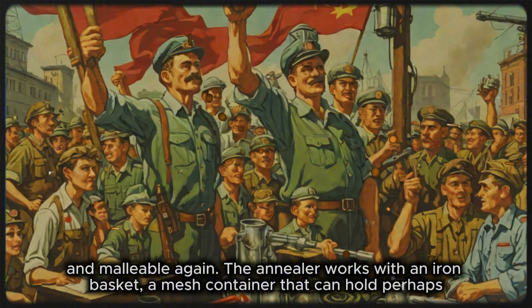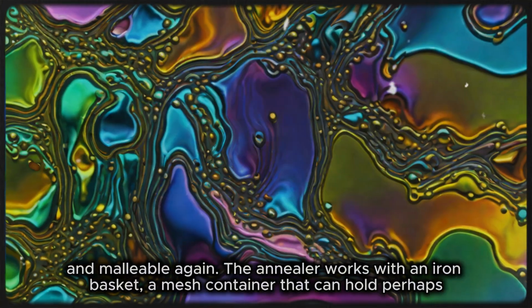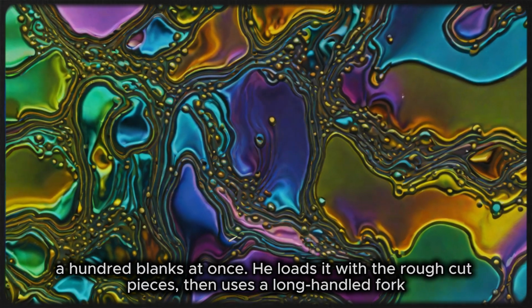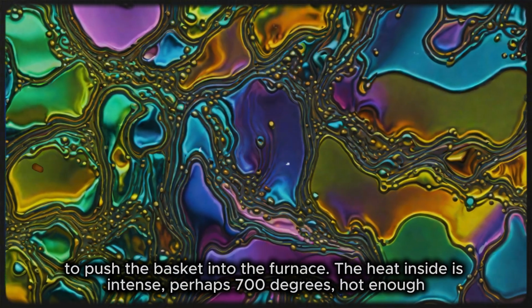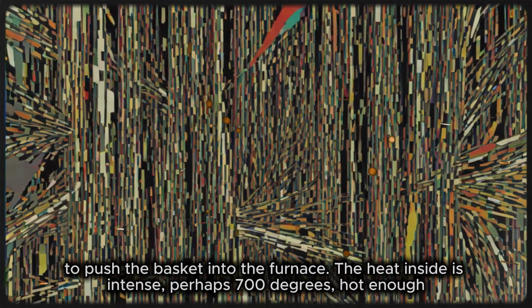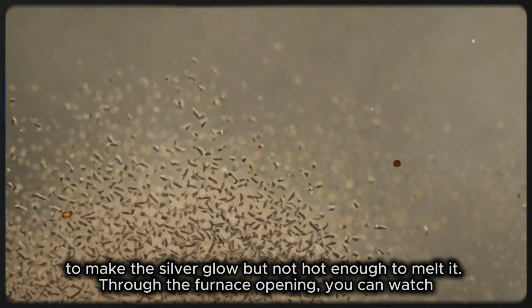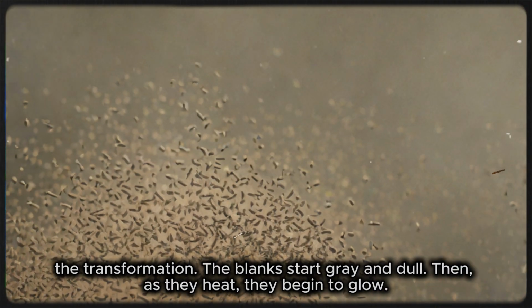The annealer works with an iron basket, a mesh container that can hold perhaps 100 blanks at once. He loads it with the rough-cut pieces, then uses a long-handled fork to push the basket into the furnace. The heat inside is intense, perhaps 700 degrees, hot enough to make the silver glow but not hot enough to melt it. Through the furnace opening, you can watch the transformation.